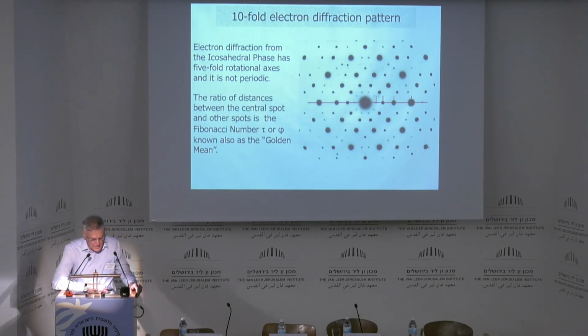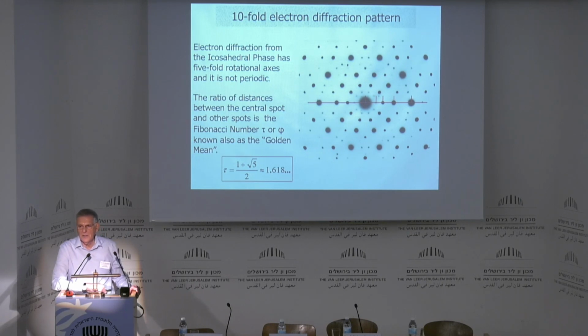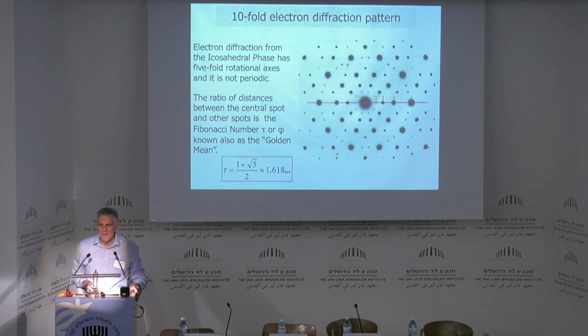The ratio of distances between the central spot and the other spot is not a rational number, but it is the Fibonacci number tau, or phi, known also as the golden mean, and this is the Fibonacci number tau, 1 plus root 5 divided by 2. Of course, you cannot get this number by measurements. This came later from theory. Irrational numbers came into crystallography. They were not there before.